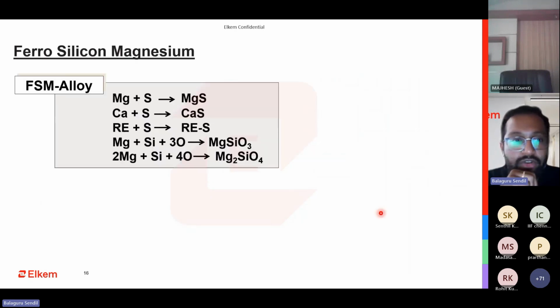The second one is using ferrosilicon magnesium. So what does ferrosilicon magnesium do? Apart from the usual magnesium, which can combine to form magnesium sulfide, which is the core of it, we have calcium also in ferrosilicon magnesium. We have rare earth also in ferrosilicon magnesium. These are the various reactions that can help in nodularizing. So this is a much more stable approach than having pure magnesium as a source of nodularization.